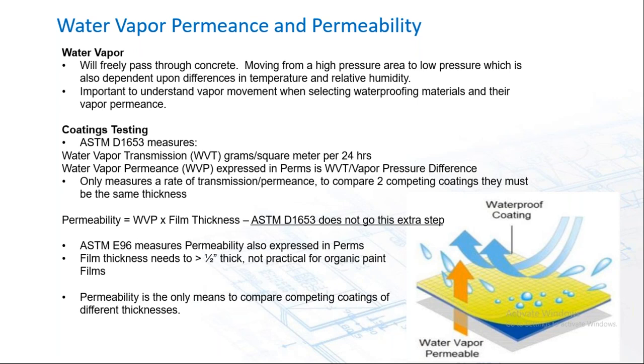calculate permeability. ASTM E96 actually measures permeability, also expressed in perms, but a film thickness needs to be greater than half an inch thick, and there are all sorts of adjustments that need to be made, and at that thickness, it's really not a practical measurement for organic paint films. Permeability is the only means to compare competing coatings at different thicknesses. So pay attention when you're looking at the test results for ASTM D1653. Manufacturers should provide you with the perms and the film thickness at which it was tested, because it is a linear relationship. Twice the thickness is half the permeability. So you need to take that into account.